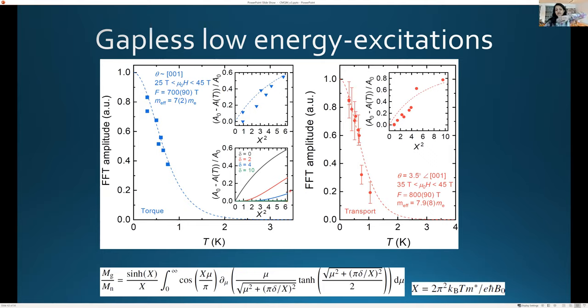So I think the reason this kind of comparison hasn't been made before is that one looks at quantum oscillations in metals. And if you see a growth in the amplitude as the temperature goes down, automatically fit LK to a gapless system. It's only in this case where we start doubting the fact that it is gapless, because that seems so strange. And we say, could it have a gap? Well, it could have a gap and still give you quantum oscillations. But the way you can tell whether it has a gap or not is whether it keeps growing at low temperatures or whether it flattens at low temperatures.